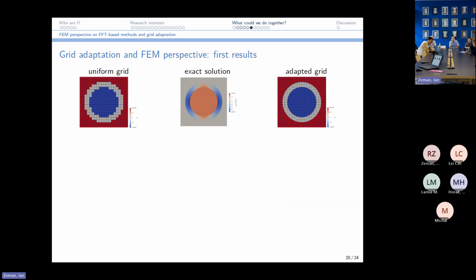So I compare what we do traditionally on a uniform grid on the left to what we could do if we move the nodes on the right, to some exact solution. So this is in conduction. The core here is insulating. The shell around it is very conductive, and it is immersed in some media which is neutral with respect to this composite inclusion. So you have no temperature gradients in the matrix around it, but you have very large gradients